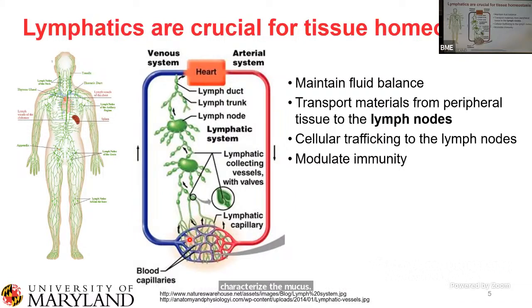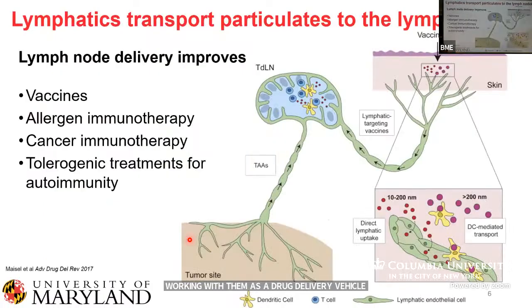And so this is part of the reason why we're really interested in trying to understand how we get things into lymphatics so that we can then actually get them to the lymph nodes. And one of the things that has been shown for about two decades now is that one of the things that gets into lymphatics is particulates. In particular, particulates of about 10 to 200, 250 nanometers in size preferentially transport into lymphatic vessels over blood capillaries. So if you inject a particle, like actually your COVID vaccines, those were nanoparticles. And it's very likely that one of the reasons why they work quite well is that they actually transported the vaccine from that peripheral injection site to the local lymph nodes.